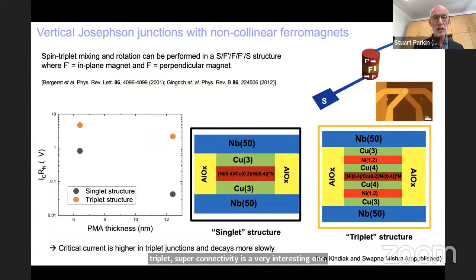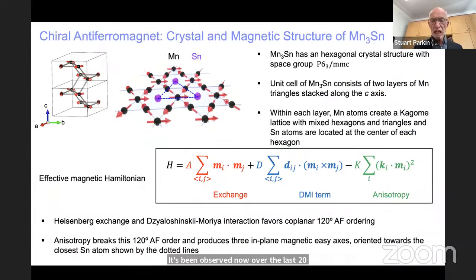It's been observed now over the last 20 years in a number of different systems. But we actually explored it in an intrinsic non-collinear system, which is a chiral antiferromagnet, which we've been exploring for a number of years. This is the system manganese-3 tin and manganese-3 germanium. In this system, you can see in a single layer, you form these triangles of manganese atoms separated by tin atoms. It's a Kagome lattice. And because of frustration, the manganese atoms have their moments oriented at 120 degrees to each other. And because of the weak Dzyaloshinskii-Moriya term from the tin component, this leads to actually a chiral triangular structure.